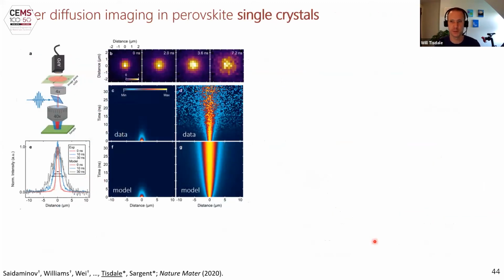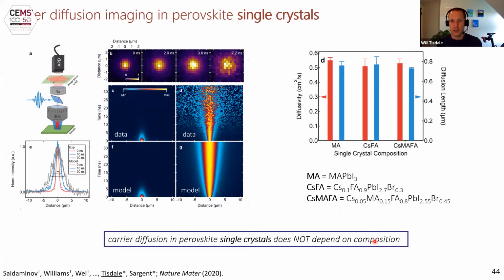What did we learn from the measurements? Well, really surprisingly, we learned that in the single crystals, the carrier diffusion does not depend on composition. This was very surprising to us. So here we're looking at 3 different samples. We're looking at methylammonium lead iodide. We're looking at a cesium formamidinium blend, so a binary cation.